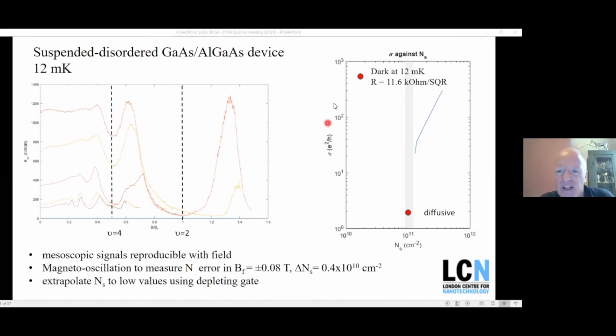So fairly well behaved at low temperatures. If we plot out conductance against carrier density, this is at 12 millikelvin. I was trying to find the critical carrier density where the device went insulating. You can see this is conductance, it's dropping down. This is the point here. So we're still just about diffusive in this device at low temperatures.